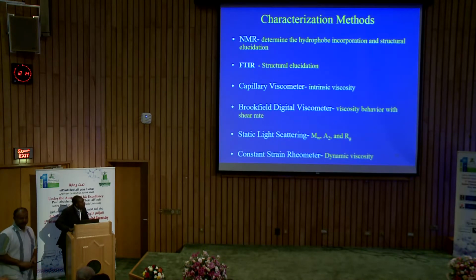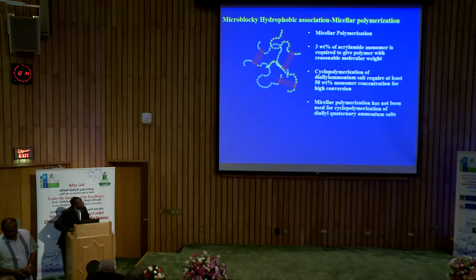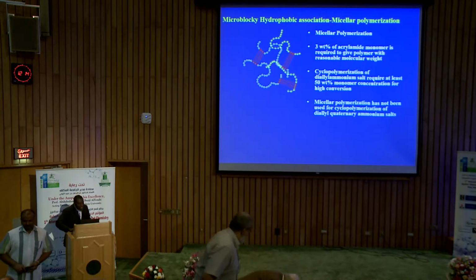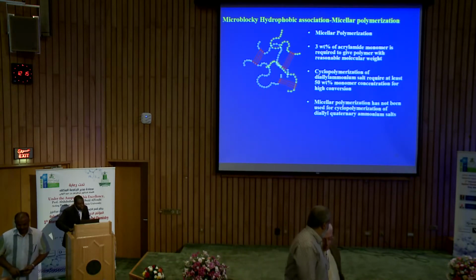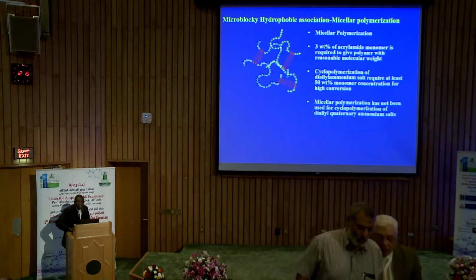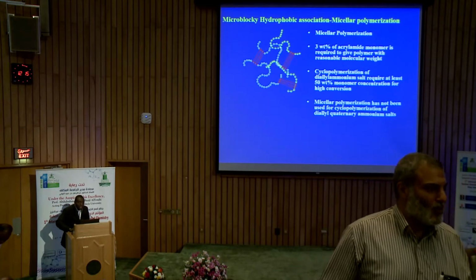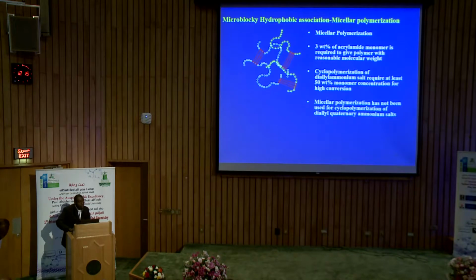And then we use constant strain rheometer for dynamic viscosity. Now, this is a typical example of micellar system where you have a hydrophobe with 3%, but in this case, the kinetics have shown that for you to have a meaningful polymerization, the percentage must be from 50 to 60%. So we cannot use micellar polymerization.